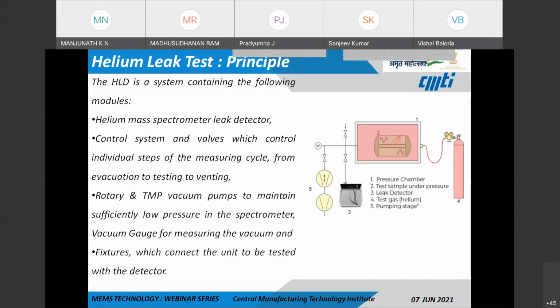So what happens is the test specimen, that is the package, is put inside the leak chamber and pumped with helium gas. Because the package is at a negative pressure, that is, it has been fabricated under a vacuum condition, and the helium is filled inside the chamber at a positive pressure, it is then left for some time, maybe for a day. We call this a pressure decay test, wherein the helium present inside the chamber will tend to pass into the package. So the pressures are monitored before and after the helium is pumped inside the chamber. This change in pressure is a gauge of the hermeticity of the package.